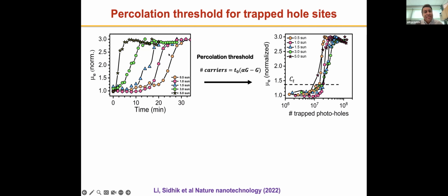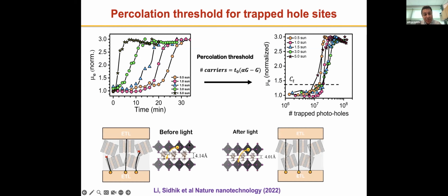And so this is all very reminiscent of, for example, if you had a film of polymer and you're trying to dope metal particles or conductive particles in it, then this is very reminiscent of a percolation type of threshold where you hit a certain concentration of conductive particles and you start to form channels in your material, which can then increase your transport. And so what's happening is after light excitation, you are opening up the channel and you're able to get much better transport.